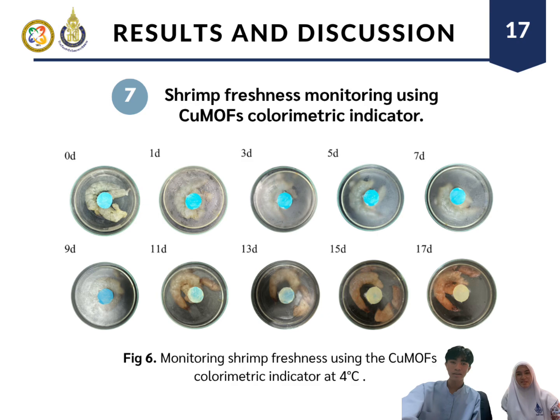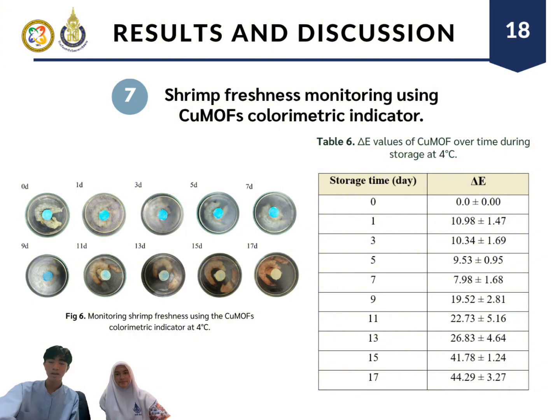For the result at 4 degrees Celsius, the delta E of the copper MOF colorimetric indicator increased with storage time, starting from 0.0 at day 0. After 9 days, the indicator began to change color, with delta E from 19.5 to 22.7, indicating the start of shrimp spoilage. After that, the delta E continued to increase, reaching 44.3 at 17 days, indicating more serious spoilage.